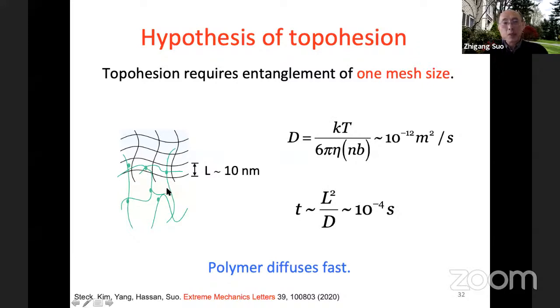So it means your polymer only needs to diffuse about a mesh size on the order of 10 nanometers. You don't need a micron, 10 micron, you don't need that—just 10 nanometers is good. This is known in polymer science, so I won't go through the deep polymer science here. But because the diffusion distance is so short, even for long chain polymers, you just need some milliseconds, less than a millisecond, to complete diffusion. So polymer diffusion is actually very fast.